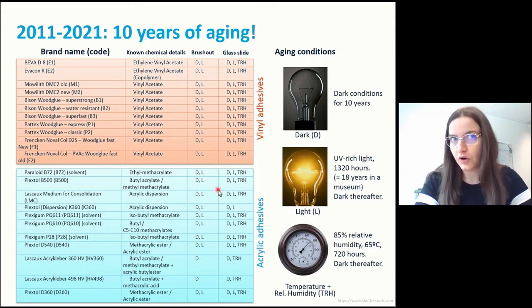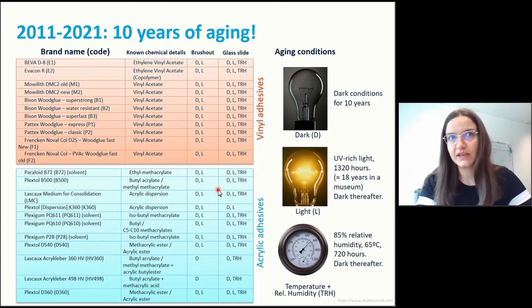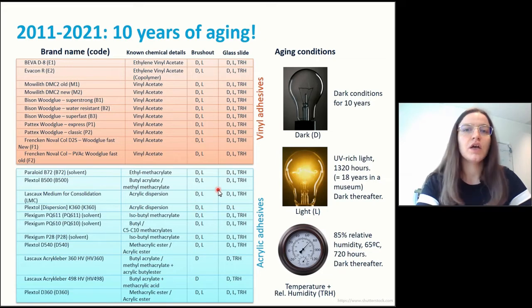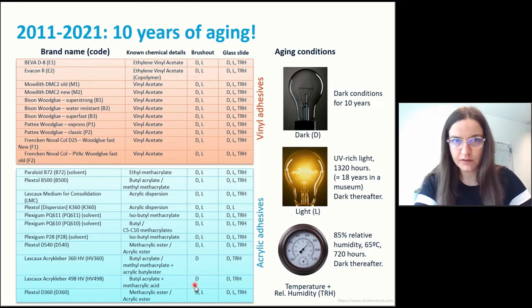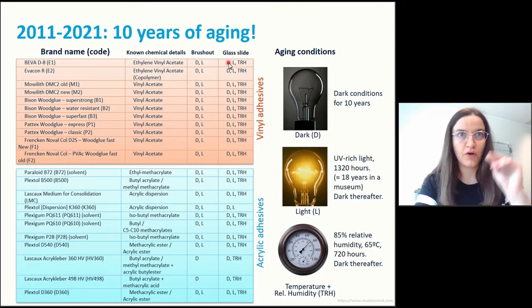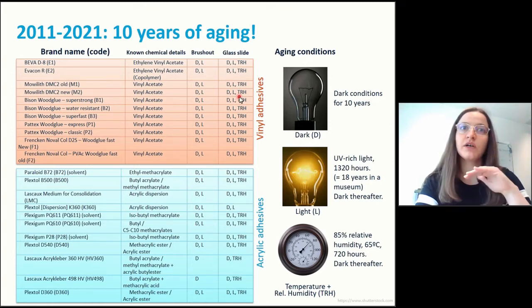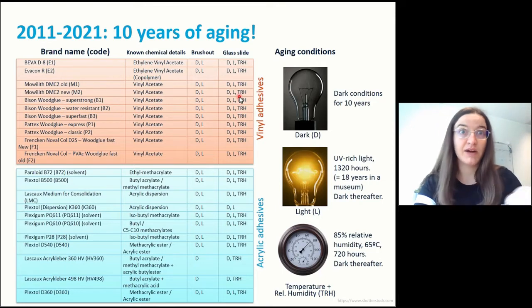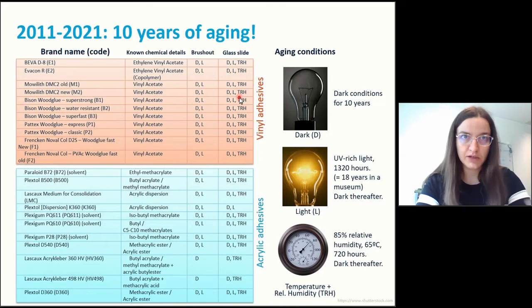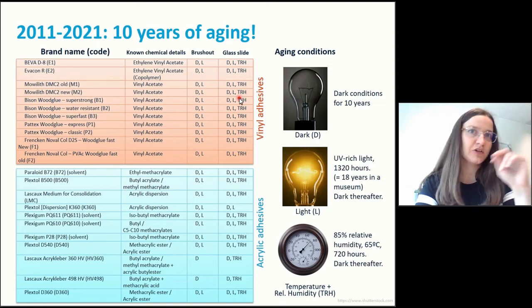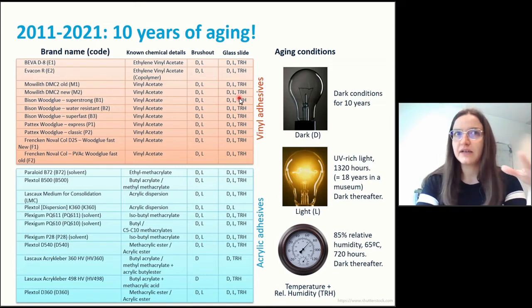And what we wanted to know was also a differentiation between what you could actually get from your adhesive in terms of different aging conditions. So one set for each of these adhesives, the one labeled as D, was left in the dark. So from the moment it was actually put on either the slide or the brush out, the samples were kept in a protected environment, no light, just in the dark, aging naturally in air condition without any big variation. This is sort of like our control with a steady aging.